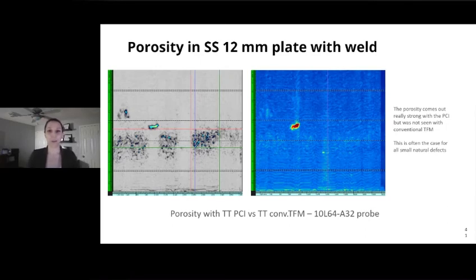Now going back for some weld defects of porosity in stainless steel. This is actually a block that we had for a very long time. We knew about this little indication there, but with amplitude, that was the only thing really making it back to the probe that had enough of a reflector to get back to the unit. As we started using PCI, we can really see now versus the noise, there's really something going on here, much more smaller scatterers, very small natural defects that were occurring in the part that we were able to pick up, as well as the larger reflector. These very small porosities in the stainless steel showed up really well. Stainless steel typically being a bit more grainy, also a bit more noisy in the TFM. It's the same for phased array, but PCI really is enjoying this. It can do the difference between what is coherent and what isn't coherent.